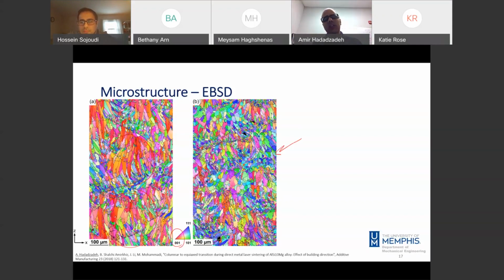By changing the morphology to equiaxed, we still have a textured material, but with less intensity, or more random texture. However, I was not able to find any significant effect of such a texture on quasi-static behavior of the material, at least in the case of SLM AlSi10Mg. In general, people, for different materials, prefer to have a more equiaxed structure rather than columnar structure, because for the columnar structure, we will have oriented properties, or a textured structure that can affect the property in different directions.